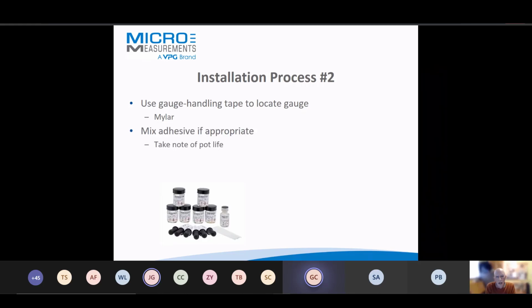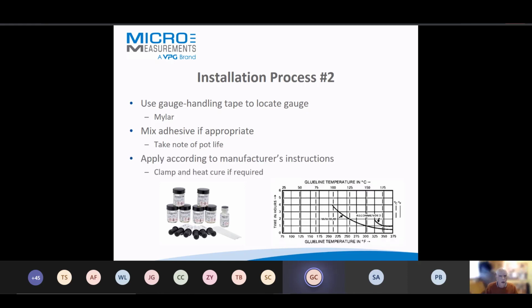Next process is you have a gauge and you want to position it on your alignment marks. First thing is we use a gauge handling tape, and we use high quality Mylar that is extremely stretch resistant. So we position it and then we get the adhesive. Depending on type of adhesive, you may need to mix it. If you mix it, most mixed adhesives have a limited pot life, anywhere between 15 minutes and 12 weeks, depending on the specific type of adhesive. And then you would apply it to the gauge and the surface according to the instructions.